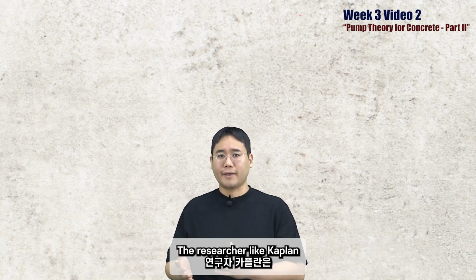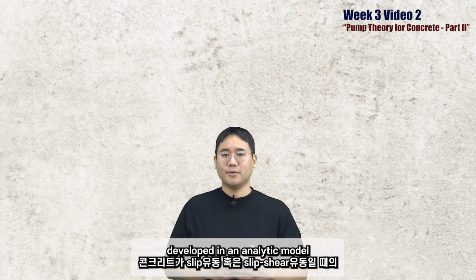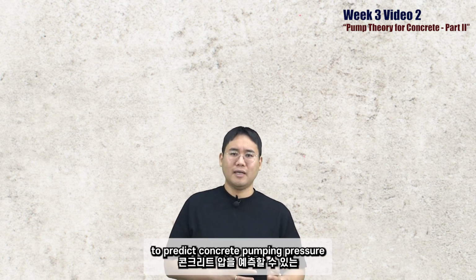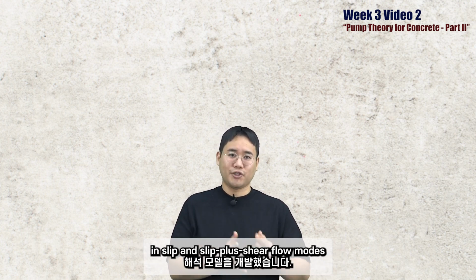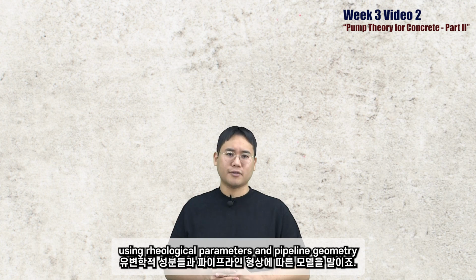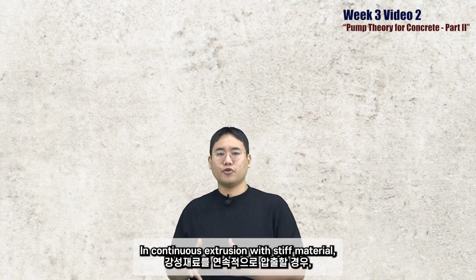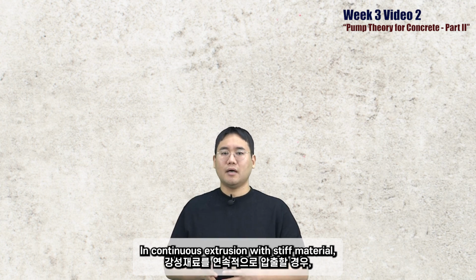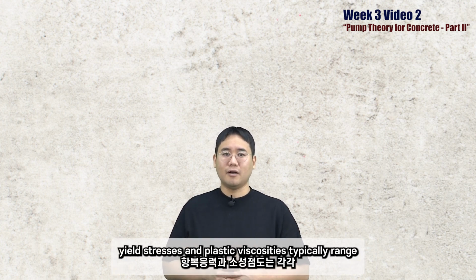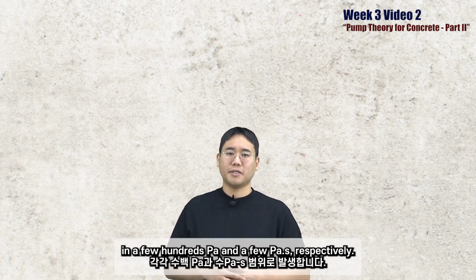Researchers like Kaplan developed an analytical model to predict concrete pumping pressure in slip and slip plus shear flow mode using rheological parameters and pipeline geometries. In continuous extrusion with stiff materials, yield stress and plastic viscosity typically range in the few hundred Pascals and few Pascal seconds, respectively.